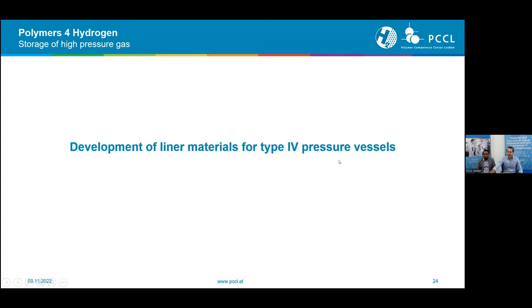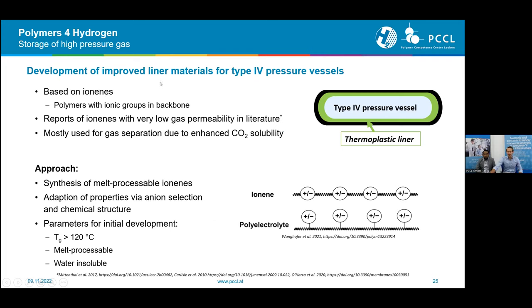So I will start with the first part, the development of the liner materials of those type 4 pressure vessels. Our approach here is to use so-called ionenes as the thermoplastic material. And those are polymers with ionic groups in the backbone. There is a schematic depiction on the lower right. The difference between ionenes and polyelectrolytes is in general that the ionenes have the ions directly in the backbone, while the polyelectrolytes usually have them in the side groups here.